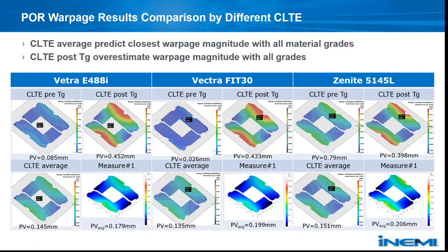So the effect of different CTE calculation options on room temperature warpage is shown on this page. All 3 CTE calculation options provide the same warpage shape as the measured data, but differ in magnitude for the 3 LCP and the POR design. The warpage predicted by the CTE pre-Tg is much lower than the measured data. And the warpage by CTE post-Tg is, on the contrary, almost twice the measured data. Meanwhile, the warpage by CTE average has about a 20% variation compared to the measured data. And the CTE average gives the closest results. Next.